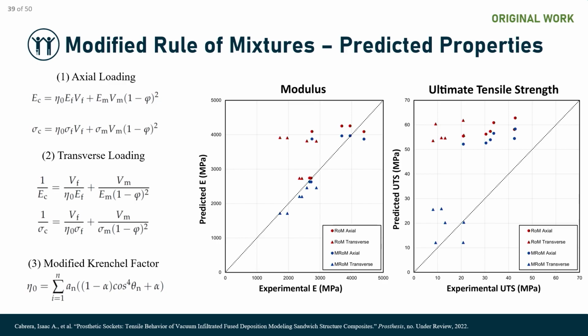And so I used the traditional rule of mixtures just as a foundation for creating models for understanding the stiffness and strength. And I added two correction factors, eta naught and this 1 minus phi squared. Essentially, the traditional rule of mixtures is, if you have a two-phase composite, two materials, you can simply, for axial loading, add up the properties, where you have the stiffness of one and the volume fraction that the composite is composed of, and add it to the volume fraction of the second material and the stiffness of the second material, and be able to get a material property of the combination.